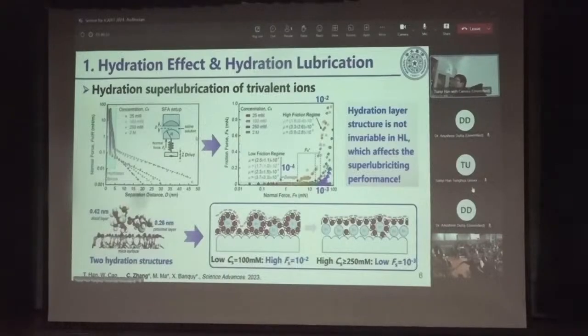Next, in the cooperation work between our group and Professor Xavier Banquy's group, Professor Xavier Banquy is a professor at the University of Montreal, Canada, we also found that strong hydration repulsion occurred with trivalent cations. The trivalent cation we used is lanthanum. We also got a very low friction coefficient during sliding, as low as 10 to the power of minus 4, sometimes minus 3 and sometimes minus 2, but all of these are very low friction coefficients.